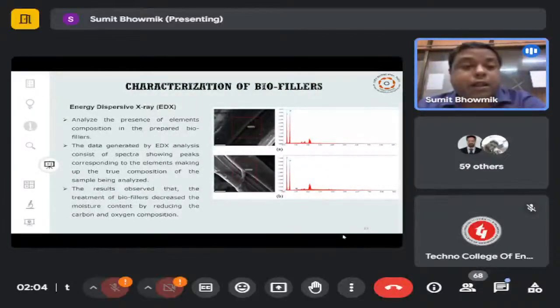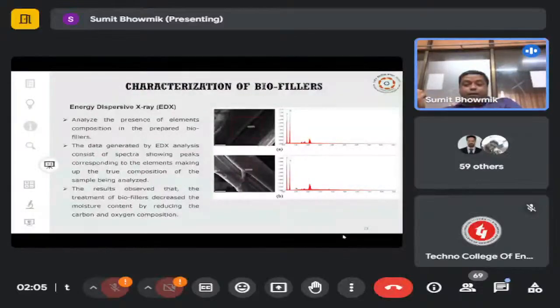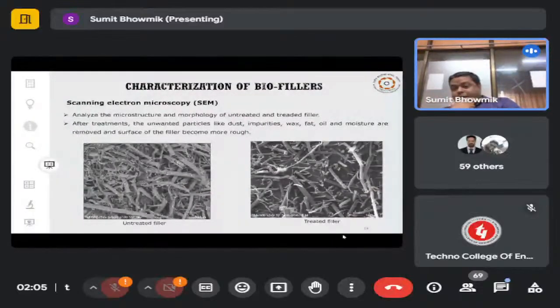In the same way, the EDAX analysis of the component has been carried out to show the peak of the composition, whether the carbon component or oxygen component is there, and how they will react, in order to decrease the moisture content or reduce the carbon or oxygen composition, so that it can be properly bonded with the epoxy matrix or resin. Now from here, if you see the microstructural analysis of the biofiller, now if you see